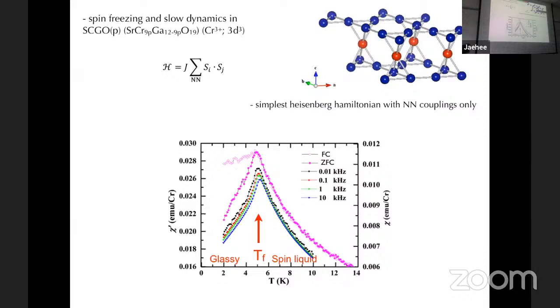And J is very strong. The Curie temperature is about 500 Kelvin. But it does not order when you cool the system, down to about 5 Kelvin. So from 500 Kelvin down to 5 Kelvin is a classical spin liquid. But then at 5 Kelvin, it undergoes some kind of freezing, as Sergey mentioned. This is spin freezing. When you do elastic neutron scattering measurements, you see this order parameter behavior below 5 Kelvin. And you can see here field-cooled and zero-field-cooled nicely.